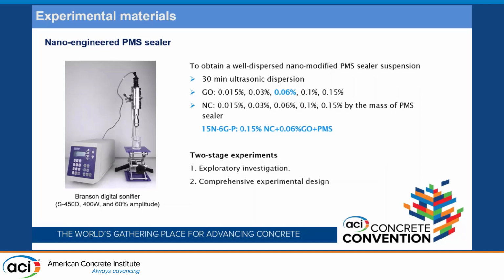Once we determine this range, then we conduct a comprehensive experimental design. That means considering all possible dosage combinations of these two nanomaterials. Here is the notation. 15N, 6G, and P means 0.15% nanoclay plus 0.06% graphene oxide in this PMS sealer. And this is the best sealer that we obtained during our experiment. And I will introduce this a lot in later slides.